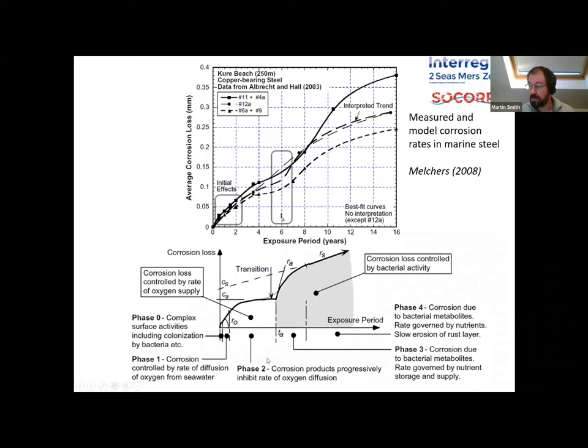And over time, eventually, we get a thick coating of corrosion products on marine steelwork, and the corrosion rate slows down because the iron oxides and oxyhydroxides are reducing the corrosion rate. But at some point, where we've had long-term monitoring of marine steelwork, we start to see a sudden dramatic increase in corrosion rate. And this is where bacterial colonization and bacteria appear to have a major role in influencing corrosion. This change in corrosion rate is because life is getting involved with these processes.